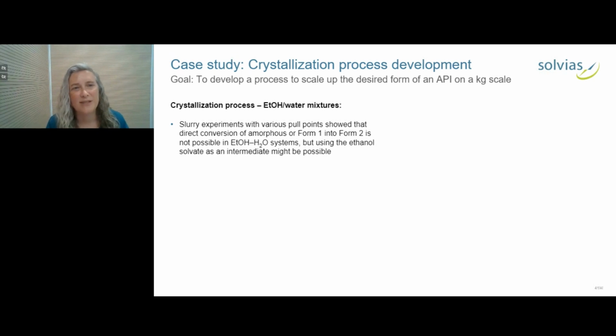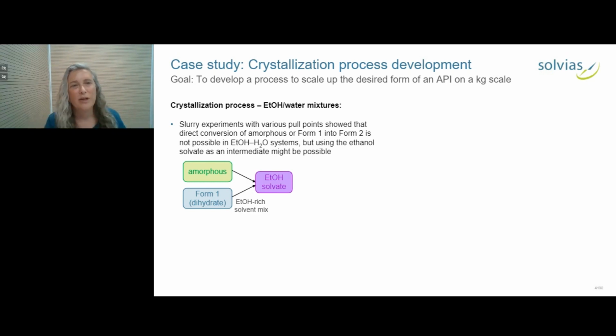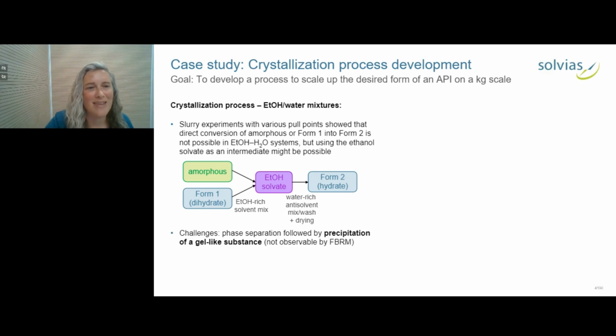We then did a series of slurry experiments with various pull points, but found it was not possible to take either the amorphous form or form 1 as the starting material and transform them directly into form 2. But what we could think about doing was using the ethanol solvate as an intermediate. The idea is you take one of your forms as the starting material, put it in an ethanol-rich solvent mixture, deliberately form the ethanol solvate, and then add water as an anti-solvent and try to convert it into form 2 in solution or possibly through the washing and drying process.